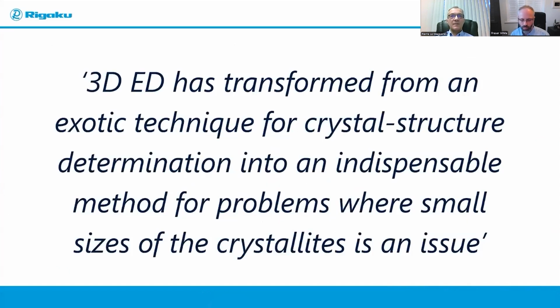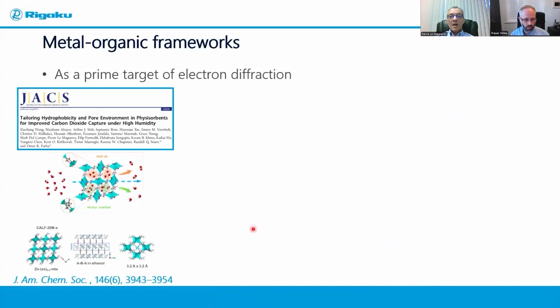Interestingly, the authors of that paper have also written the following quote in their publication, and I will read it with you if you don't mind. So 3D ED, which is another way of calling MicroED, has transformed from an exotic technique for crystal structure determination into an indispensable method for problems where small size of the crystallites is an issue. And that totally echoes what I explained a few minutes ago about how electron diffraction is able to analyze submicron particles. So we have also solved the crystal structure of many MOF samples, activated or not, using electron diffraction.